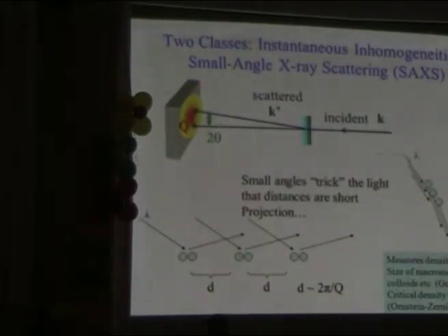Okay, so small angle X-ray scattering. So this is now done with X-rays. We have very short wavelengths. But by going to very small angles, we trick the light to see correlations even at very long distances. I will assume that you're familiar with small angle neutron scattering or X-ray scattering. Basically what we will see here are density inhomogeneities in the liquid. And we can extract also the length scale of them.